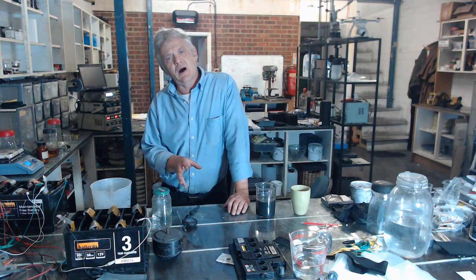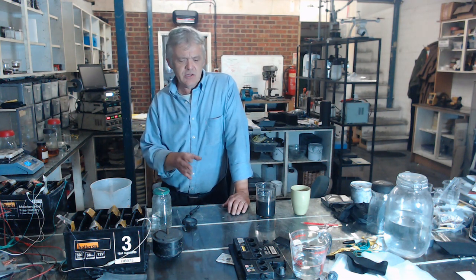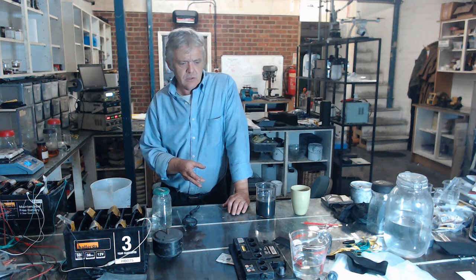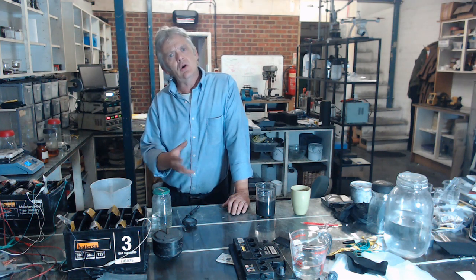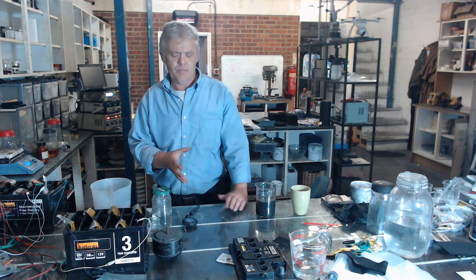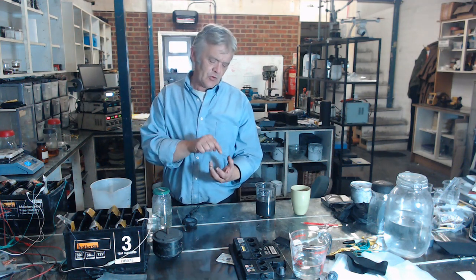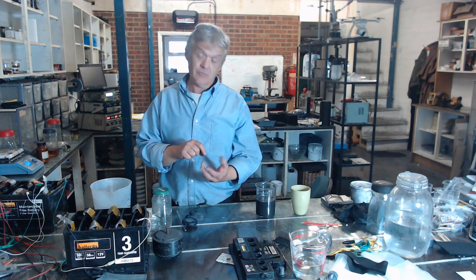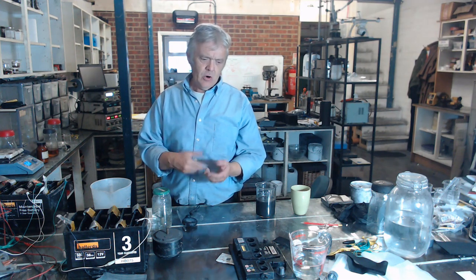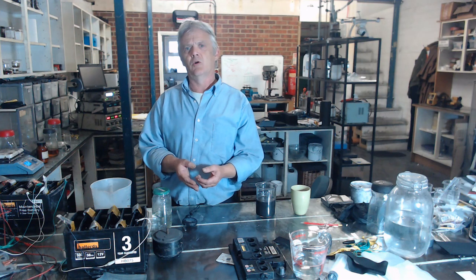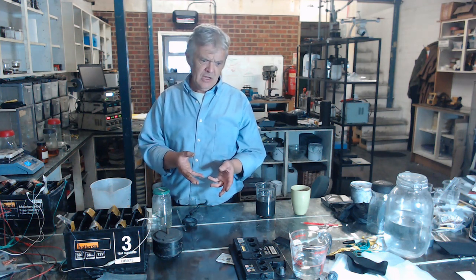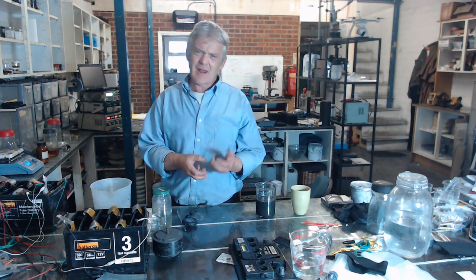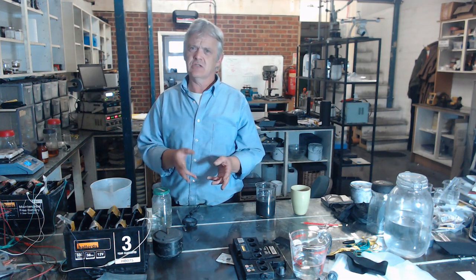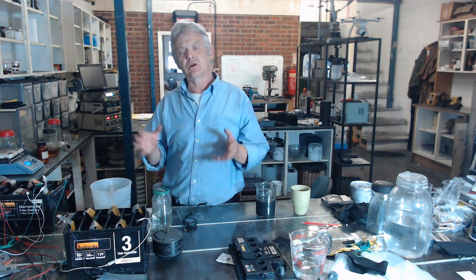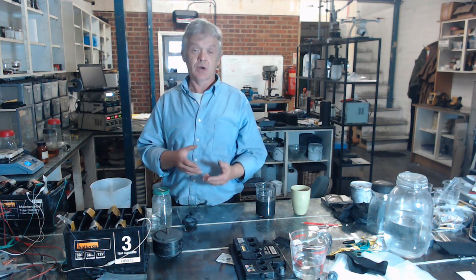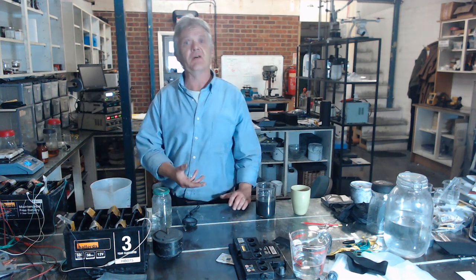What you mostly find is an awful lot of flake graphite. These are individual crystals that have formed in the rock and are locked in with the rock. So if you pick a piece up and slice through it, you'll see graphite flakes of relatively large size dotted around that rock. The amorphous graphite is thought to be a metamorphic formation from things like coal. And it forms a very black and sooty material, which is kind of like 60-70% graphite, and the rest is rubbish, and that brings down the price of amorphous graphite because there's an awful lot of stuff in it that's quite hard to separate.